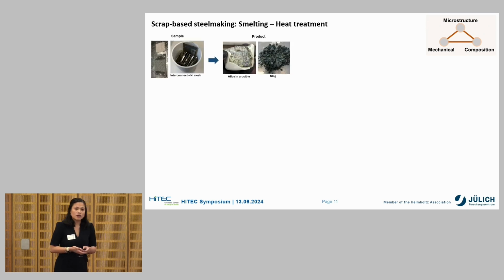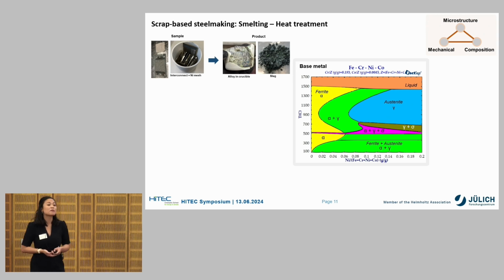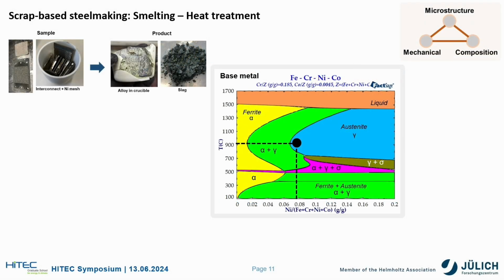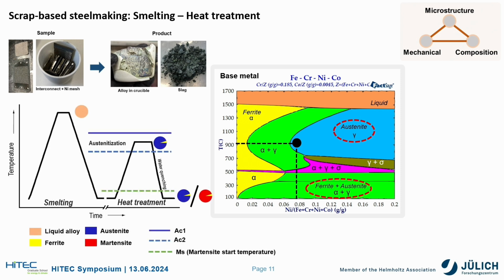So if we melt down this entire interconnect assembly, do we produce a fully austenitic steel? To answer this question, we refer to the equilibrium phase diagram of the sample and see at which temperature ranges the austenite phase is stable. And according to this, austenite is stable at temperatures above 900 degrees Celsius. Furthermore, it is also thermodynamically possible to observe austenite at room temperature, but this time ferrite also forms alongside this phase. So we melted the sample, held it at its austenitization temperature, and then water quenched it to freeze the microstructure. By doing so, two things can happen.